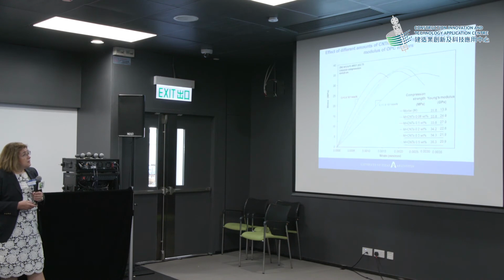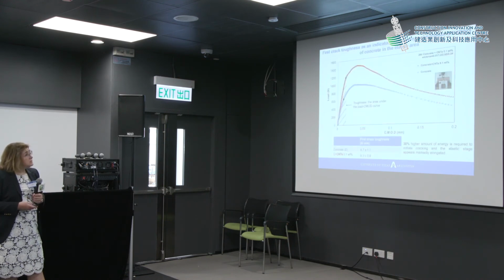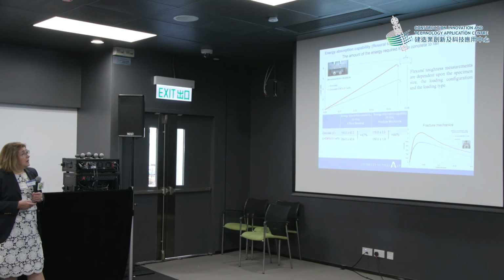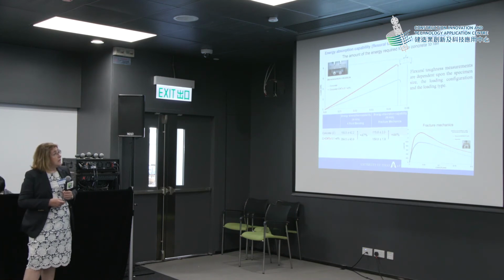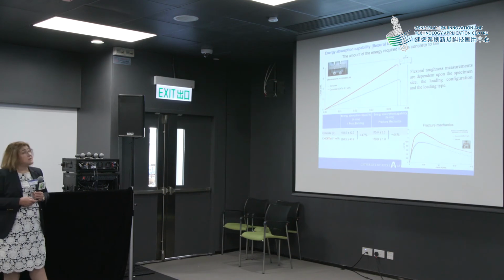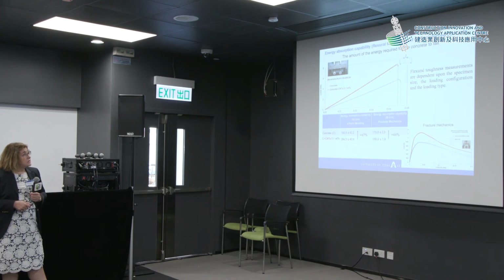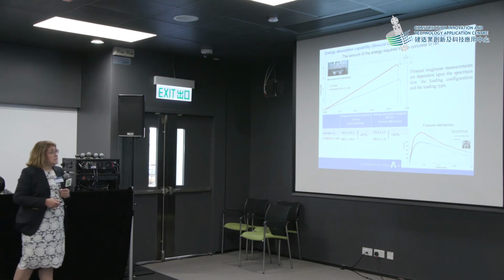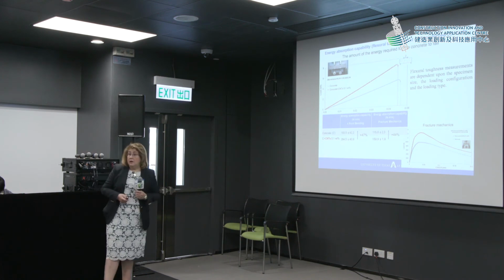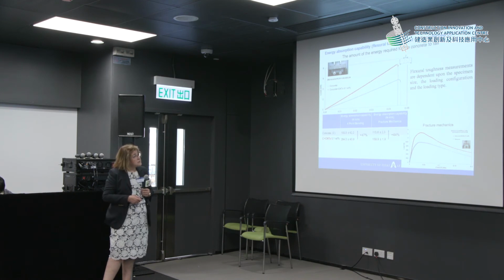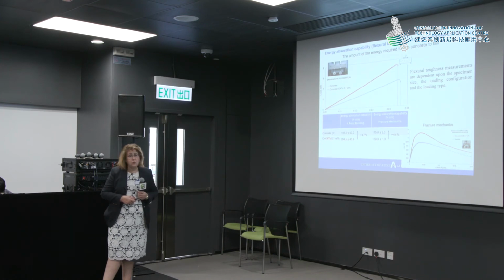We double-checked our experiments with 4-point bending experiments, only to find out that the concretes with 0.1 carbon nanotubes, the nano-reinforced concretes, are giving us flexural toughness that is about 50% higher. And what you see here is a comparison between fracture mechanics tests and 4-point bending tests.